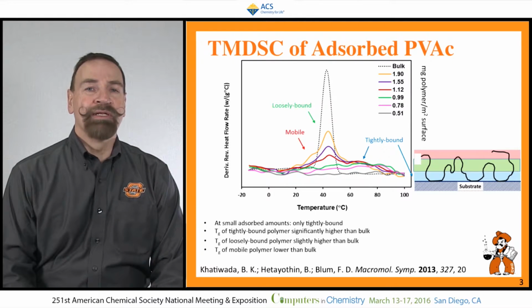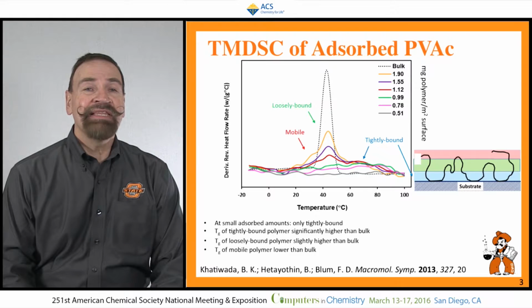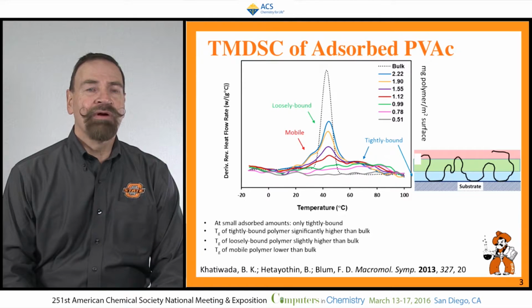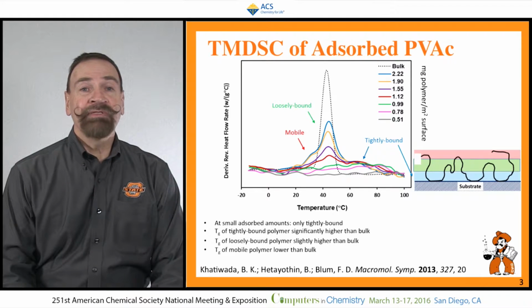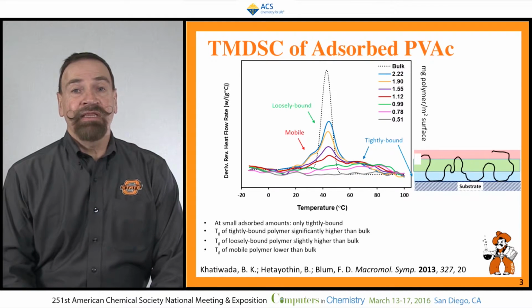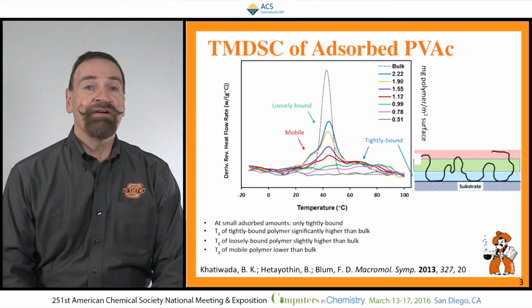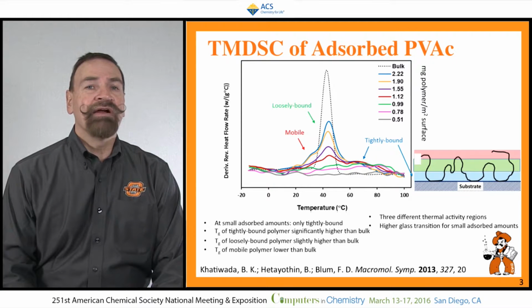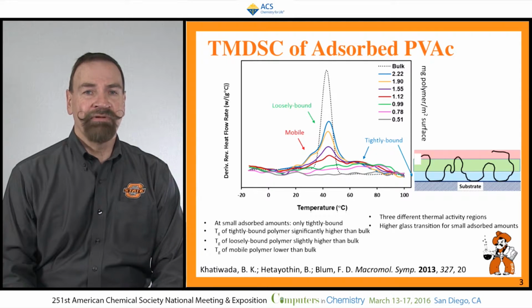They're actually more mobile. These more mobile polymers tend to be at the air interface, and if I add a little more polymer to the sample, what I see is that for practical purposes, the intensity under the tightly bound polymer regime is roughly constant. The mobile polymer region is roughly constant. In other words, the substrate interface is fixed, the air interface is fixed, and what I'm doing when I'm adding more polymer is adding more loosely bound or bulk-like polymer. So this loosely bound polymer is different, and there are three distinct kinds of behaviors that we see.